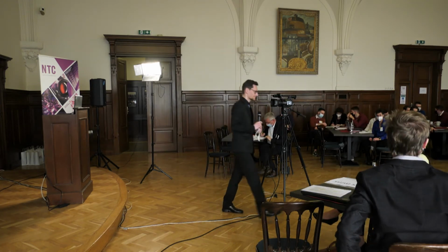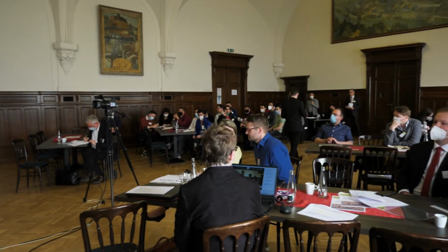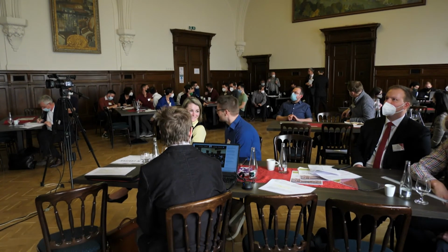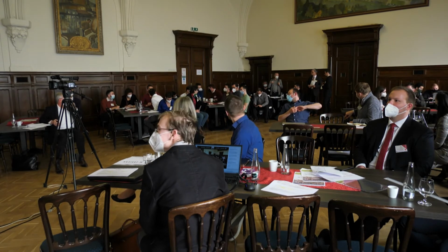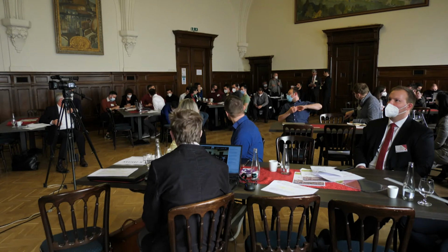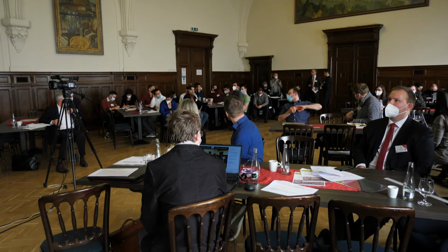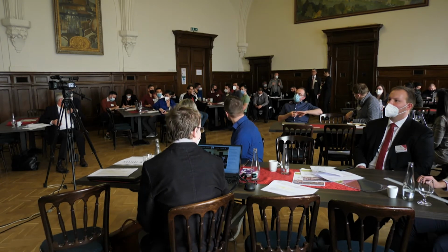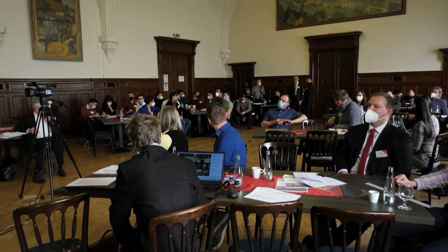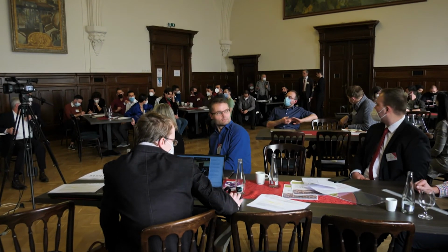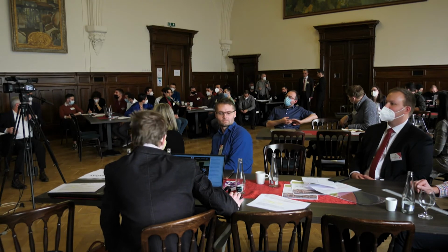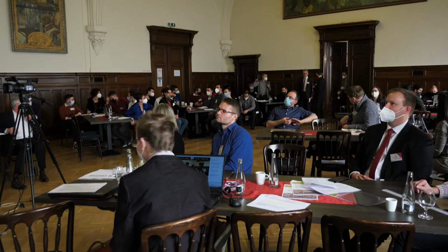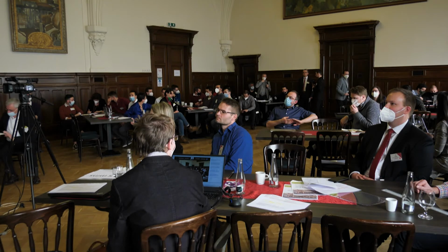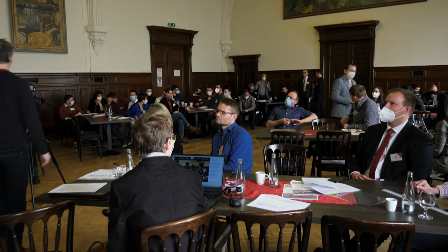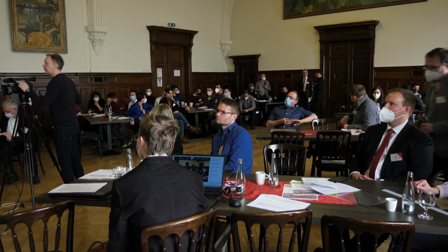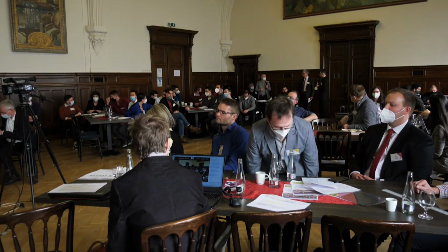Okay, there was a next question in the back. Thank you for the talk. This is a remark to your presentation, but also to the previous presentation in the morning. I think it makes sense to always put the current density when you're talking about the voltage efficiency. That strongly depends on whether you're running at 10 milliamps per square centimeter, 50 or 200. You can crash any voltage efficiency if you go to very high current densities, which is, on the other hand, needed. If you want a good commercial product, you need to have a high current density. So I would recommend to always give this information on the slides when you're talking about voltage efficiency. Maybe it is somewhere in the earlier slides and I missed it, but it's helpful for the reader to always see the current density. Yeah, it wasn't there in this presentation, and it was 100 milliamperes. Okay, that's reasonable, thank you.